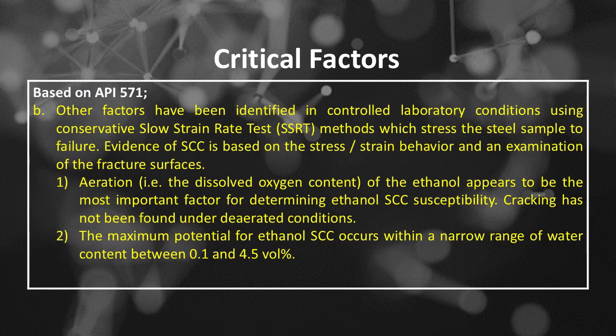Number B, other factors have been identified in controlled laboratory conditions using conservative slow strain rate test, SSRT, methods which stress the steel sample to failure. Evidence of SCC is based on the stress or strain behavior and an examination of the fracture surfaces. Number 1, aeration, i.e. the dissolved oxygen content of the ethanol appears to be the most important factor for determining ethanol SCC susceptibility. Cracking has not been found under deaerated conditions.